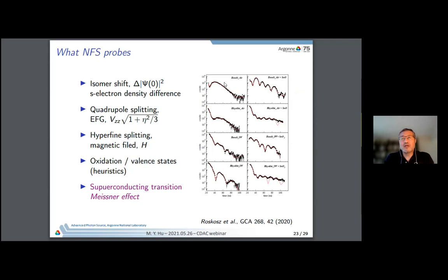So you measure some sample by itself, you see some time behavior. But in order to measure the isomer shift, you have to put in a reference. So you see we have some oxides with a well-defined line, so you can put another line in, and you get a kind of beating to measure the difference. And then the quadrupole splitting actually measures the electric field gradient. Again, that's what we measure.